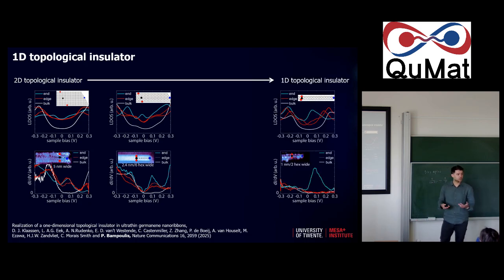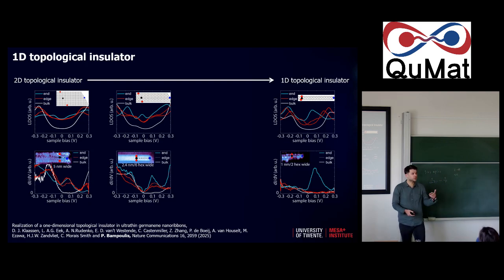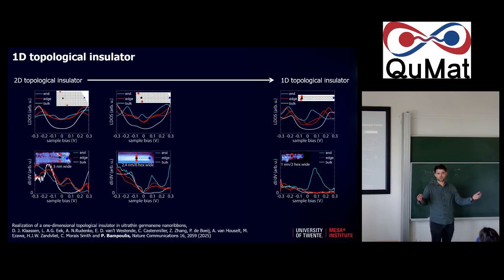And now we go to the case of a very narrow nanoribbon. This is 2 hexagons wide, and now you see that both in the experiment and in the theory, the edge states are gapped. So edge and bulk have approximately the same density of states, but at the end of the nanoribbon, you end up with a very sharp peak in the density of states, again reminiscent of these 0D modes that you have at the end of the nanoribbon. So we have a very good agreement between theory and experiment that this phase transition leads to the emergence of 0D states that are localized at the end of the nanoribbon.